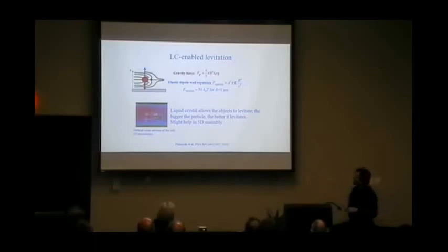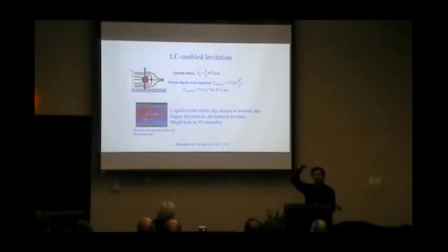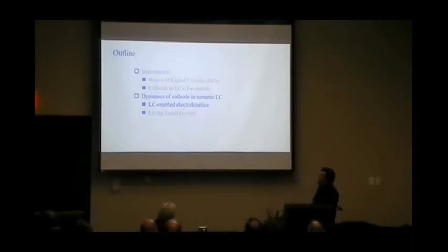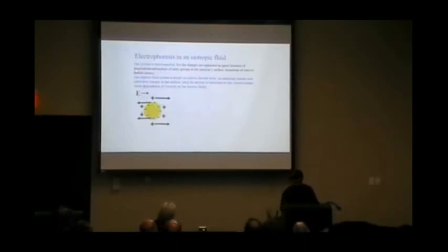By the way, the simple model predicts that the bigger the particle, the better it levitates. And this is experimental verification. On the right, you see slightly bigger particle, and it levitates at a higher z as compared to the smaller particle. So with this, knowing that we can easily keep the particles in the bulk of our cells, we decided to do our first experiments with electrophoresis of colloids in the liquid crystal environment.